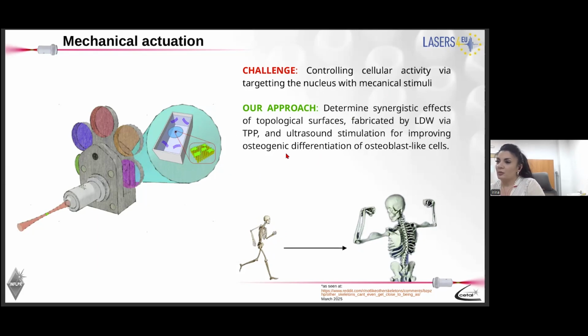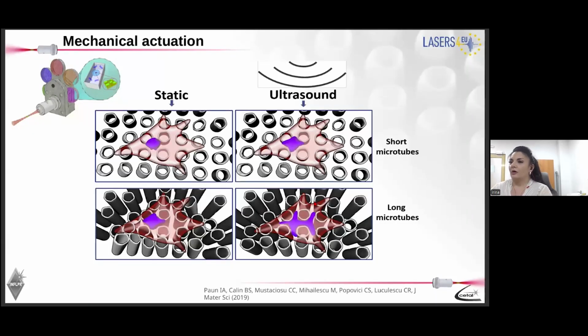We address this issue by a synergy between 3D topographies that we made by laser lithography technique that I showed you before. We seeded cells on top of these topographies, and we just moved them in an ultrasound bath. This is the base principle of this part of our work. In a starting condition, we have made vertical microtubes of different heights, and we placed the osteoblast cells on them.